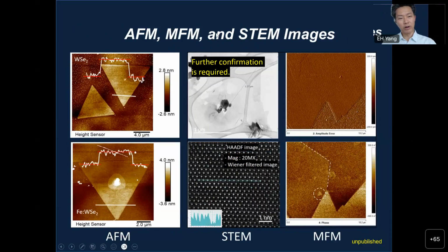We are working on AFM imaging, AFM mapping. On the right, it is magnetic force microscopy mapping here. And on the top right, this is a height sensor image, basically, okay? Just shows the height. On the bottom right, this is a phase image. But it's the same material, same area. But unlike the top right, from the bottom right, you see some boundaries. And we hope that these are the magnetic domain boundary.